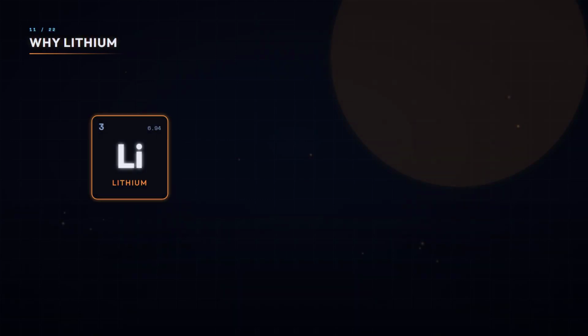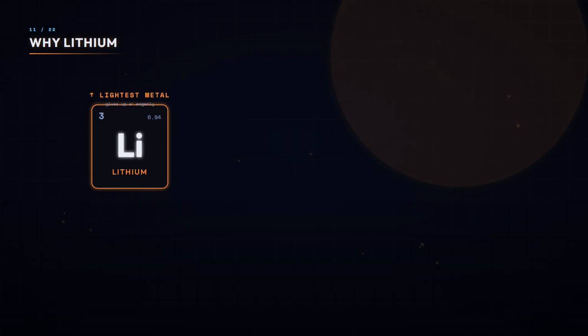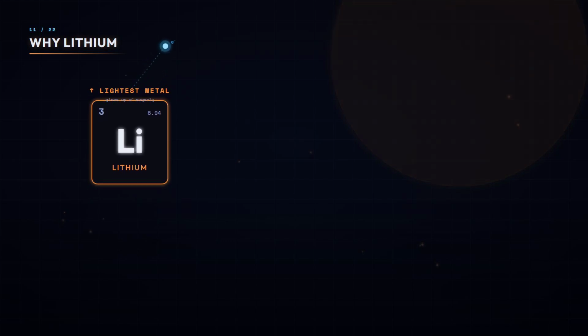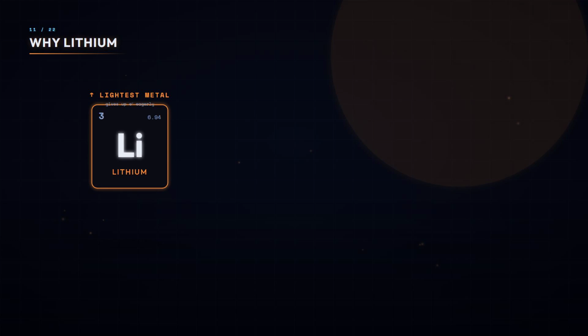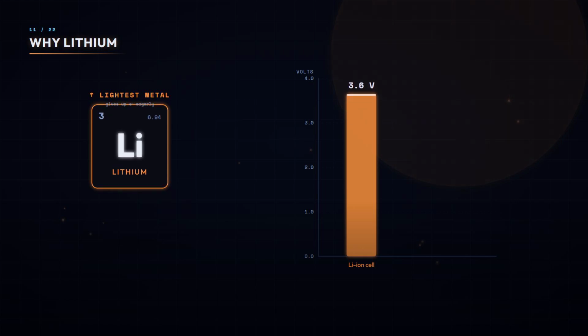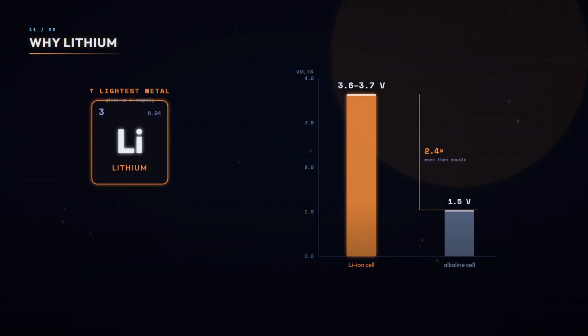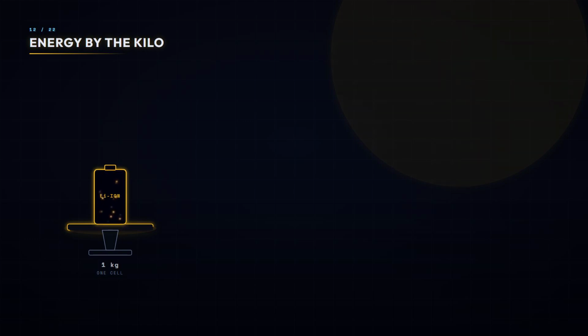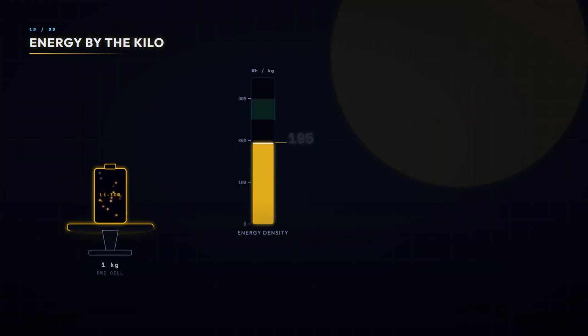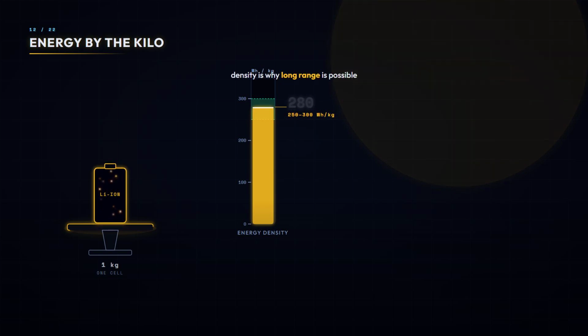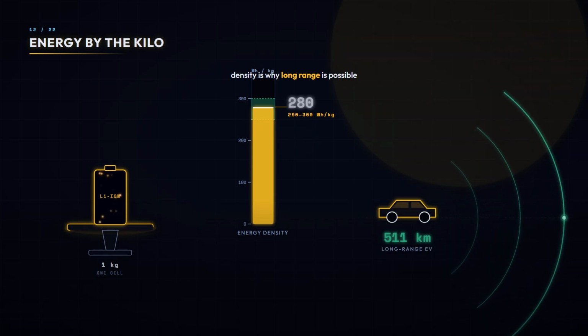Why lithium at all? It's the lightest metal, and it gives up its electron more eagerly than almost anything. That pushes each cell to about 3.6 to 3.7 volts, more than double a standard alkaline cell's 1.5. That high voltage is why lithium-ion packs so much energy into so little weight. Today's best cells reach around 250 to 300 watt-hours per kilogram. That density is the single reason long-range electric cars are even possible.